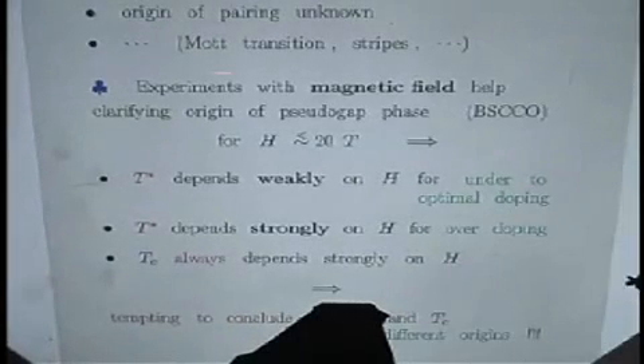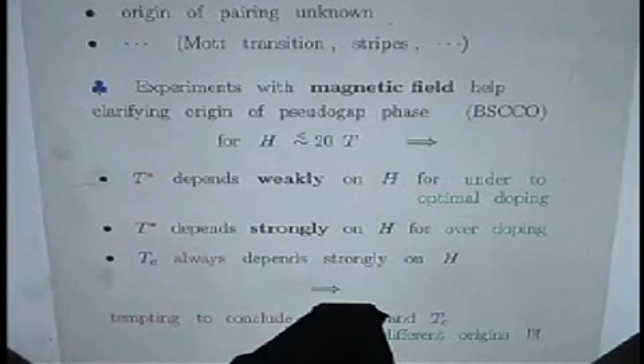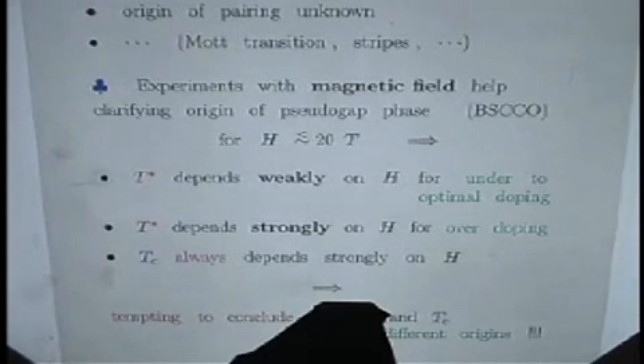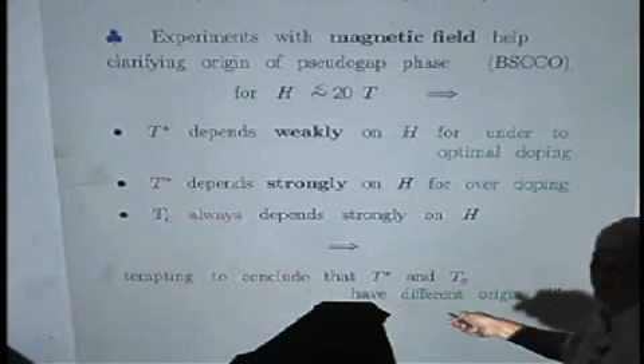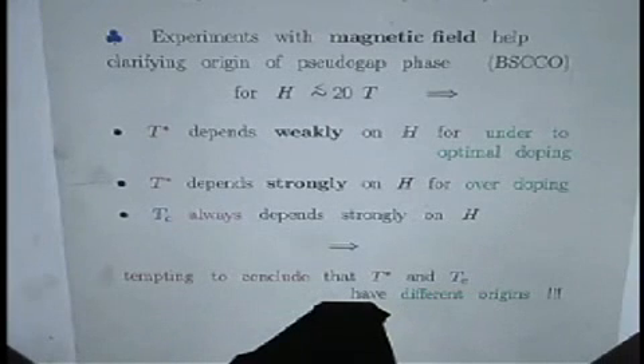Well, probably the magnetic field can help understanding the origin of this phase, the pseudo-gap phase. And experiments done up to 20 Tesla have essentially obtained this result. T star depends weakly on H, where the system is in the underdoped region up to optimal doping essentially, whereas it depends strongly on H for the overdoped region, and the critical temperature TC always depends strongly on the magnetic field. From these two different results, one is tempted to conclude that the two temperatures have different physical origin.